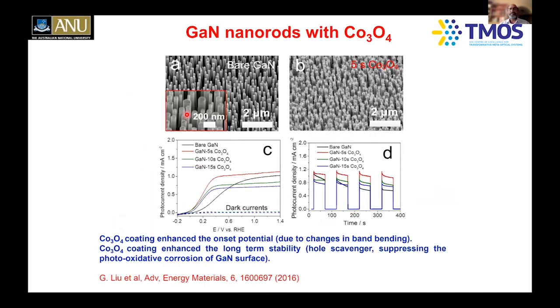So here's a case example of the gallium nitride nanorods, which we have been using. Gallium nitride is very difficult to etch chemically normally. But it turns out that when we were using these things as photoanodes, their stability was not very good, and we had to coat these with cobalt oxide, which acts like a co-catalyst and also a hole scavenger, suppressing the photooxidative corrosion of gallium nitride surfaces, and we were able to show that you can really get a very stable performance from these semiconductor anodes, for example, here.